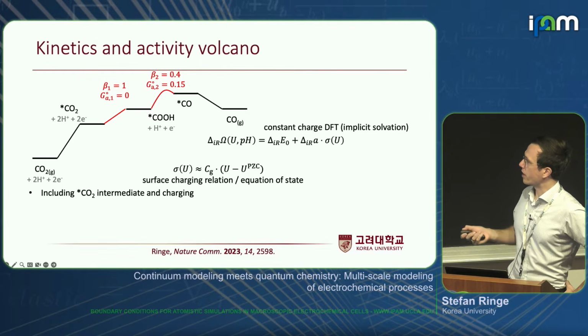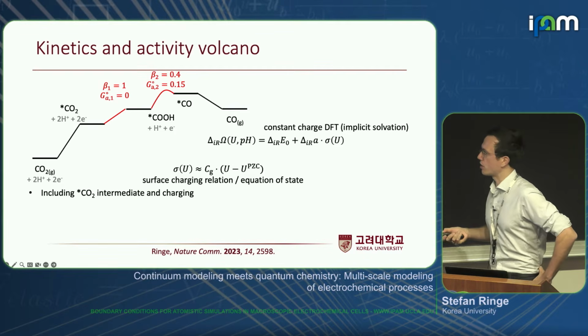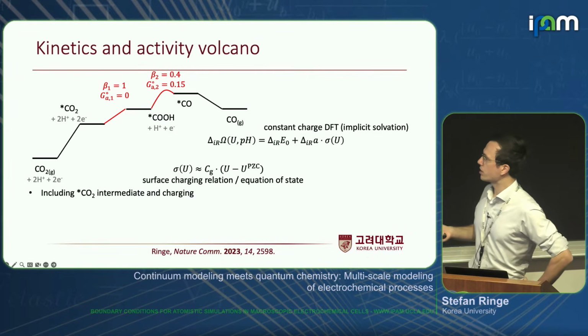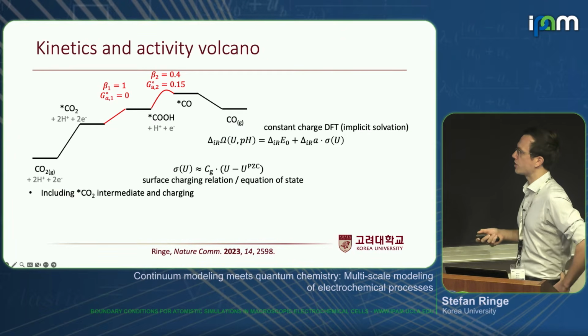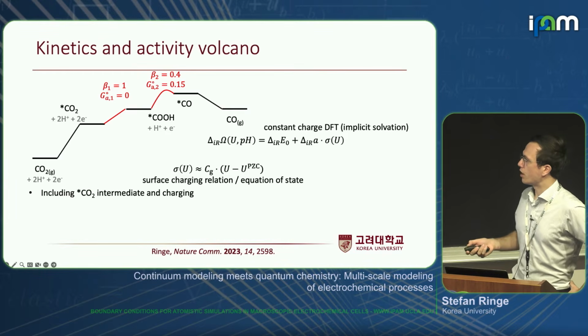So I went ahead and calculated all these energies as a function of charge. So you have all these charge-dependent energies, and only considering the linear term here, because the quadratic term is usually not that significant. I used here the linear surface charge relation, equation of state. So a simple plate capacitor model in this case to estimate the surface charge.